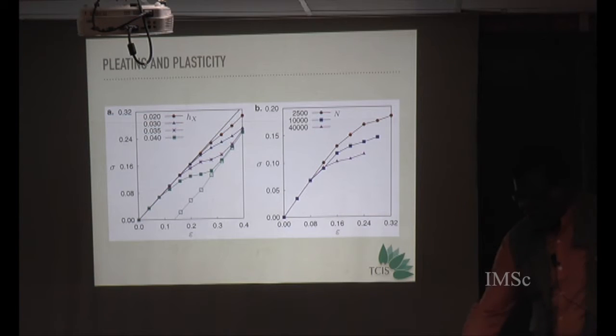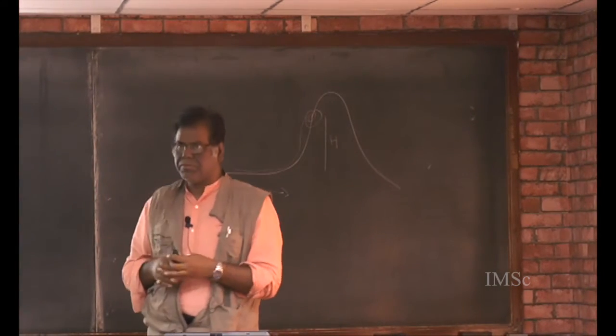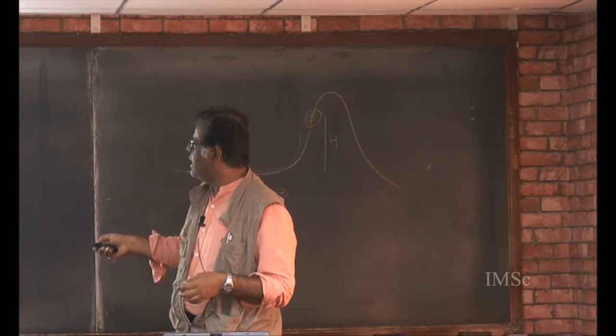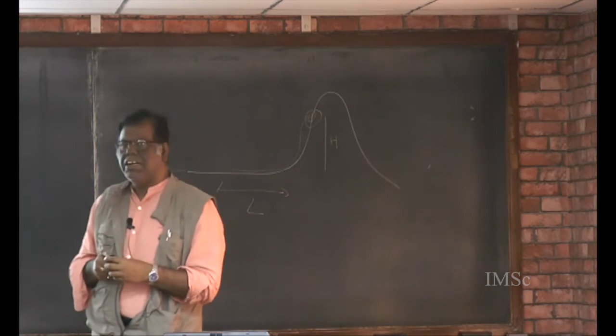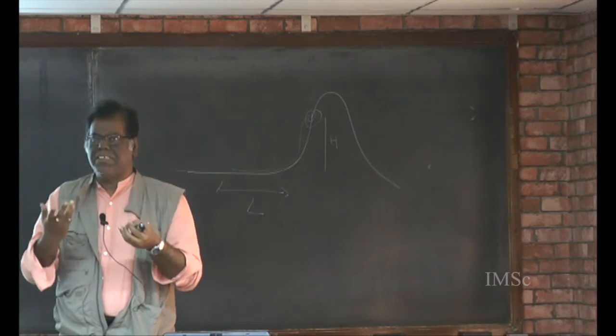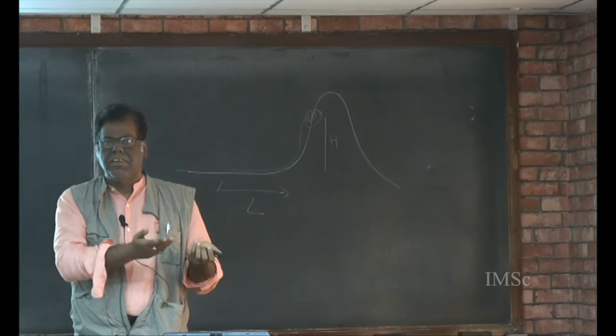What I would like to point out again here is that these different curves are at different values of h, but you can see that h does not change the elastic constants at all, because you can see that from the dynamical matrix, which you can calculate analytically. h contributes to order q squared in the dynamical matrix. So elastic constants are of order q, so to lowest order there is no contribution. Okay, and you can again do finite size scaling. So you can see that the stress versus strain is just a manifestation of this equilibrium transition which is underneath.